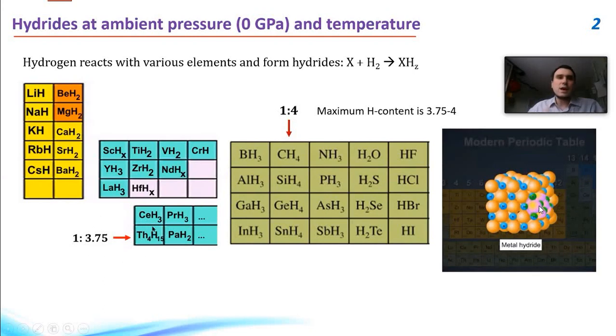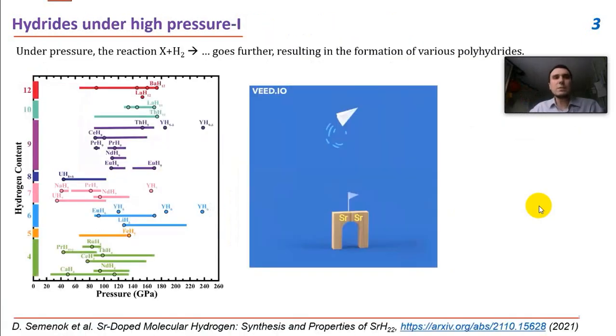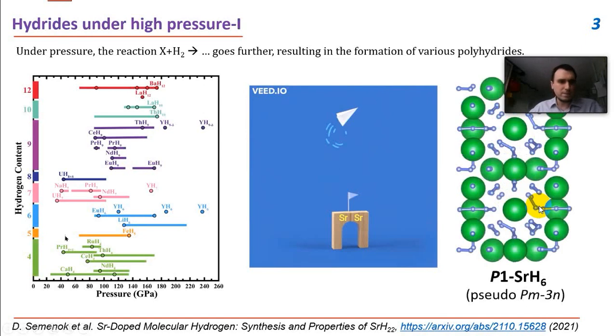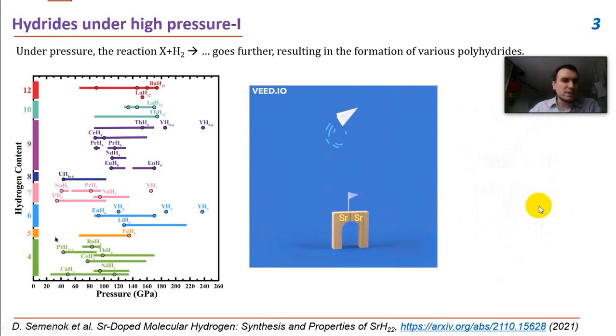Okay, let's see now what will happen if we increase the pressure of hydrogen. Which compounds can we get, which compounds can we obtain. So under high pressure, about 1 million atmospheres, if we increase the concentration of hydrogen, we can first get a family of tetrahydrides. It's a tetragonal compound such as praseodymium H4, calcium H4, neodymium H4.